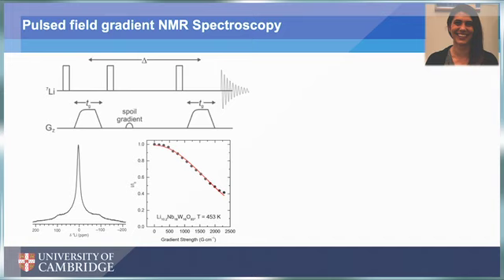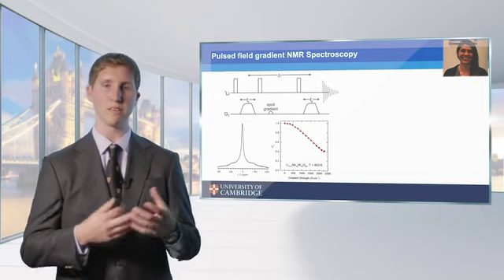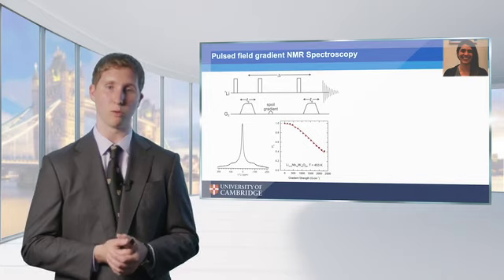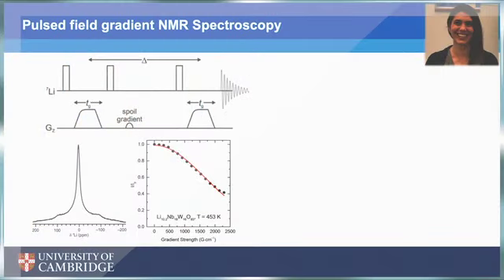The big advantage of pulsed field gradient NMR spectroscopy is that you're able to look specifically at the lithium ions and nothing else. So the contributions we're seeing here, even in a mixed conductor, are coming purely from lithium motion. And it's a direct way to measure the diffusion of this material. So in the bottom left here, we've got a conventional NMR spectrum of our lithiated niobium tungsten oxide. And what we do is we pulse the field gradient on this. We give it some time for the lithium ions to move, and then we refocus and remeasure that signal. And so basically, the more that those lithium ions are moving, the more the signal is going to dephase and experience a different field. And so we'll expect the intensity to decrease.